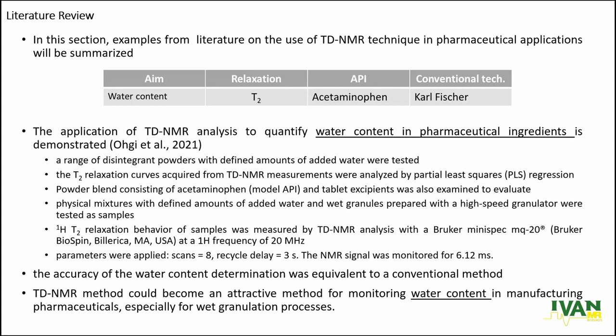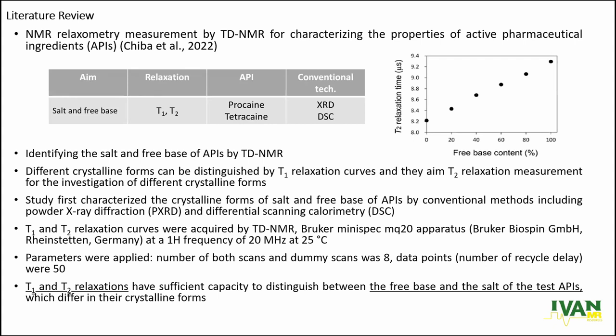Because of the time limitation, I'm not going into details of the parameters of the NMR, but you can see them in the slides. In another study, they used TD-NMR for characterizing the active pharmaceutical ingredients. You can see it in the table. They studied the identification of the salt and free base of APIs by TD-NMR. Different crystalline forms can be distinguished by T1 relaxation curves. We know that. And they aimed at T2 relaxation measurements for the investigation of different crystalline forms. The study first characterized the crystalline form of the salt and free base of the APIs by conventional methods, XRD and DSC. Then T1 and T2 relaxation curves were obtained.